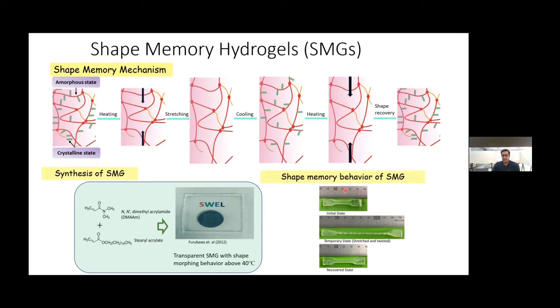And you can see this is the initial state of the shape memory material. If you increase the temperature above 40 degrees Celsius, that means above the glass transition temperature of this material, the crystal molecules melt, and you can extend or stretch or twist whatever you like with this material. And if you decrease the temperature lower than 40 degrees Celsius, then the crystal reforms again and you will get the temporary shape. And if you give heat again, you will get this recovered state.